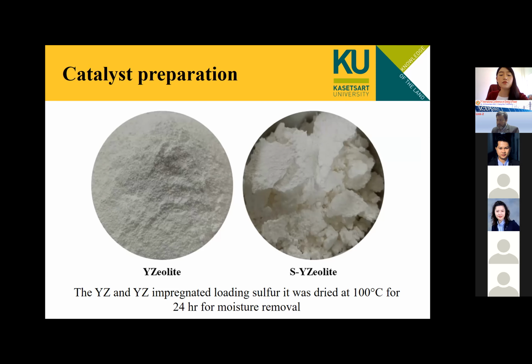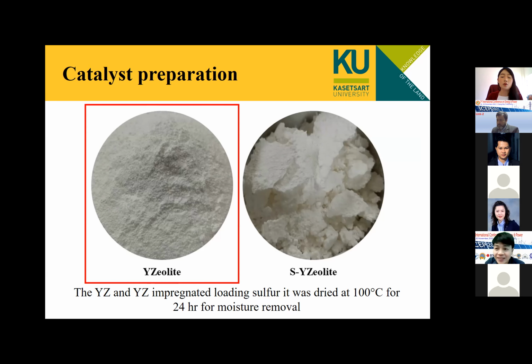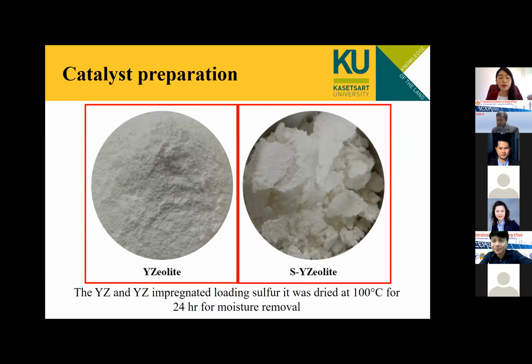As you see from the picture, this one is the original Y zeolite, and this one is Y zeolite impregnated with sulfur. It is washed and dried at 100 Celsius for 24 hours for moisture removal.